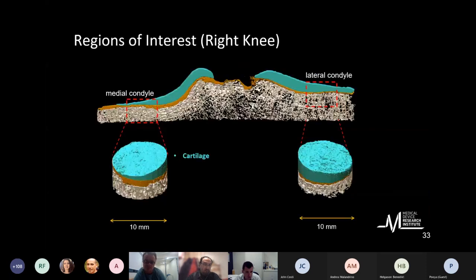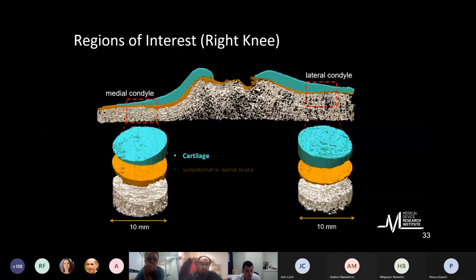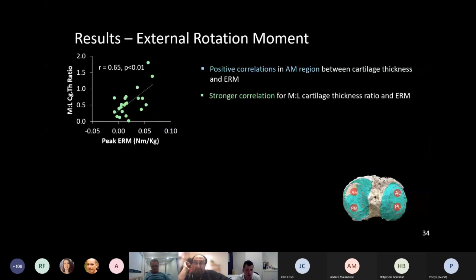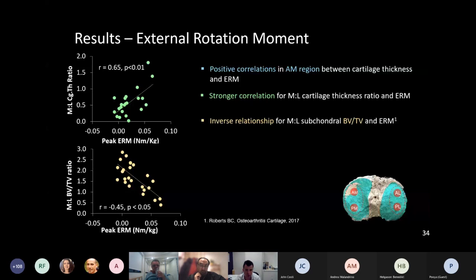If we separate the tibial plateau into cartilage, subchondral trabecular bone, and in between the subchondral cortical bone, which is what we saw before, now we can look at all these three things at once. And what we found is that these relationships that we found with the medial to lateral cartilage ratio and the external rotation moment are opposite to what we found in the bone. So regions with thicker cartilage have thinner bone. There must be something there which drives the joint as a whole, which decreases the cartilage and increases the bone underneath.